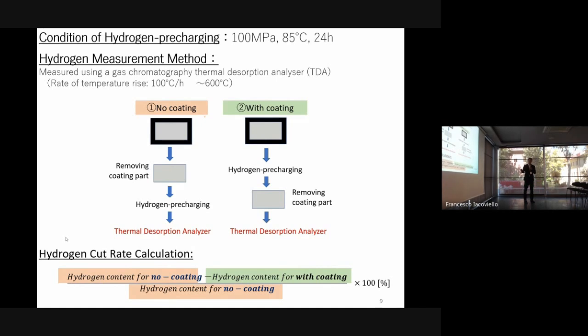This is the condition of hydrogen precharging. The specimens were exposed to 100 megapascal high pressure hydrogen gas at 85 degrees Celsius, which is the maximum temperature used in hydrogen stations, for 1 day. Hydrogen content was measured by a gas chromatography type thermal desorption analyzer, TDA. There are two types of specimen. At first, uncoated specimen, hydrogen precharging, and hydrogen measurement.